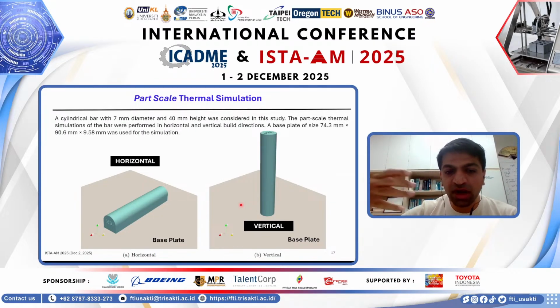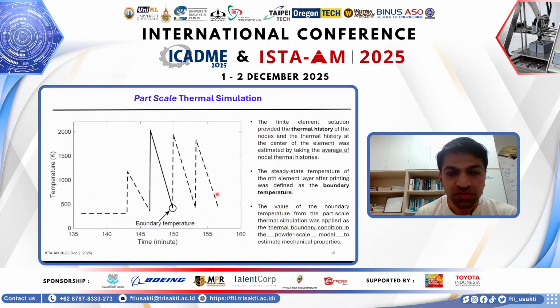So there's sufficient area for thermal heat to be dissipated from the 3D printed stack. In the vertical growth situation, the surface area or interfacial area of contact with the base plate is much smaller, and therefore it's very difficult for heat to be dissipated during the melt pool solidification process. Therefore, we will see a big change in the mechanical properties for these 2 scenarios, depending on whether the growth is horizontal or vertical for the same cylinder.